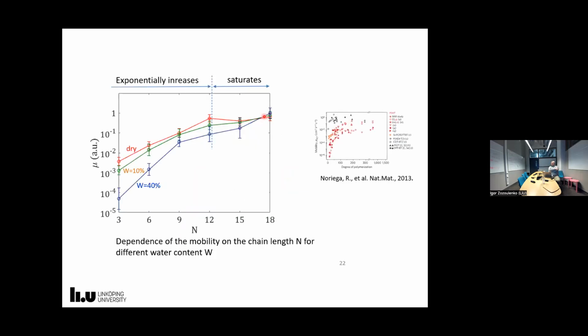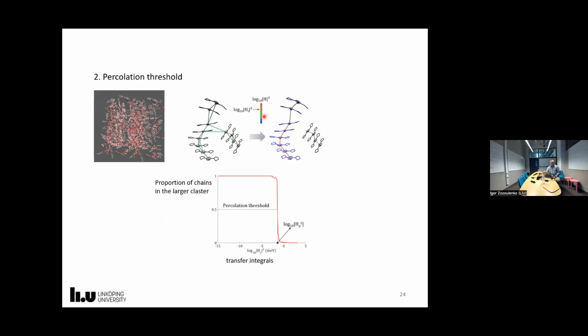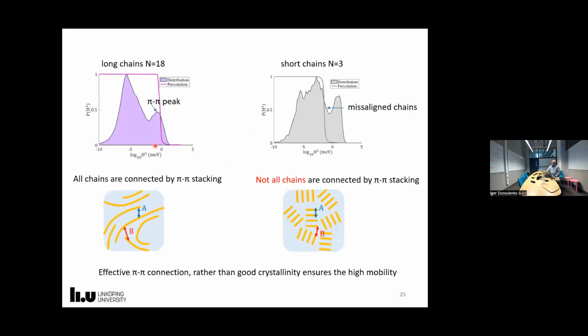But the most important part is to understand this. As I said, in order to understand this, we performed a so-called percolative analysis. Because of the lack of time, I cannot really go into details, so I jump directly to the conclusion, which is visualized here. What we found is that if chains are long enough, they are all connected by pi stacking. This is illustrated here. You can start at any part of any chain, and then move through this pi stacking through the entire crystal, the entire thin film.